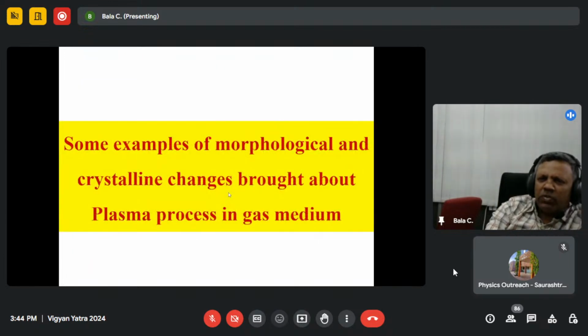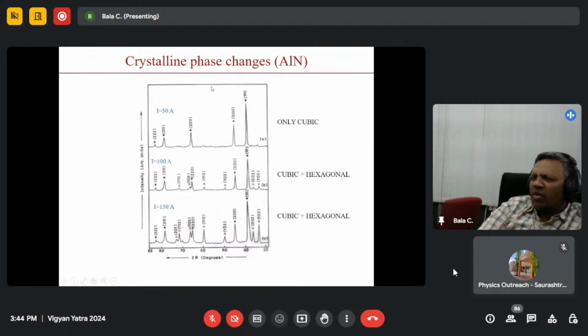I'll give some examples of using plasma in a gas phase experiment. You can get different sizes, shapes, and also crystalline phases. Using the same materials, everything the same, just by changing the plasma current, you can get different crystalline phases. Like this one is all cubic phase. If you change the current, you get a mix of cubic and hexagonal. If you change the current further, you see this one, which was not existent before, starts coming up.